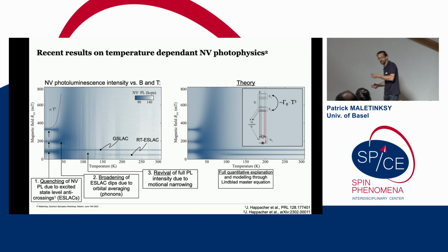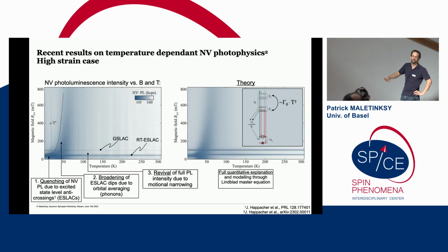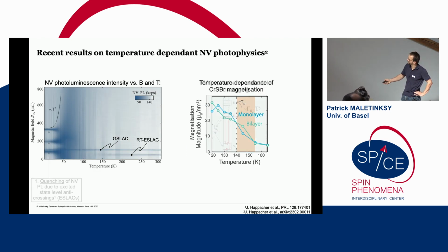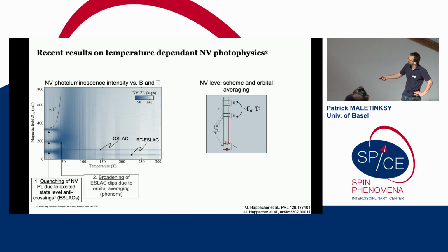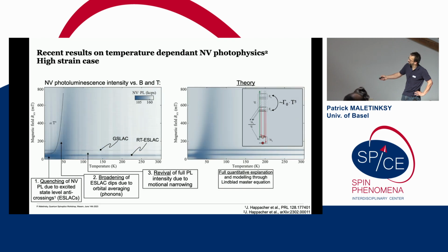And now that we have that understanding, this helps us a great deal in our low temperature NV magnetometry experiments because we know now which regions to avoid. So everything that's dark here, you can essentially not measure at, so you want to go out of there, or you want to tune the NV so that it performs better, and you can do that, for instance, by going to different strain values. So these are data for one strain value, low strain, and high strain, so you see that you can sort of shift these bad regions here.